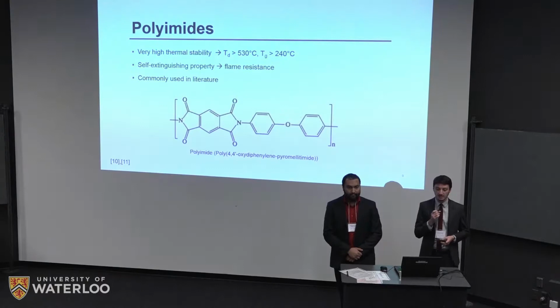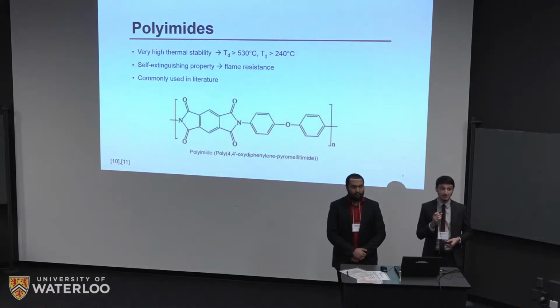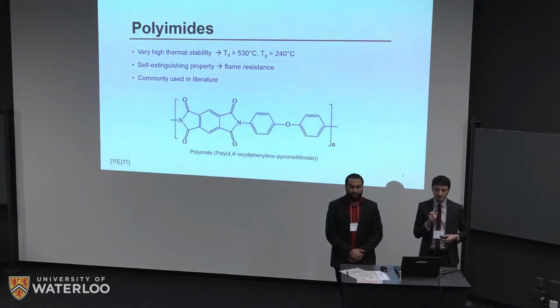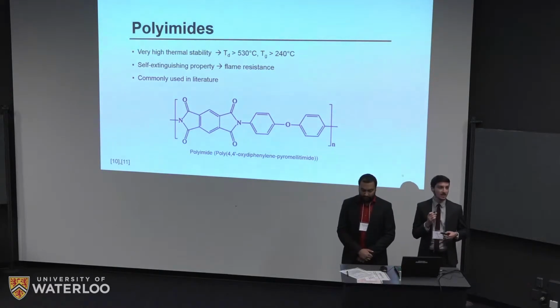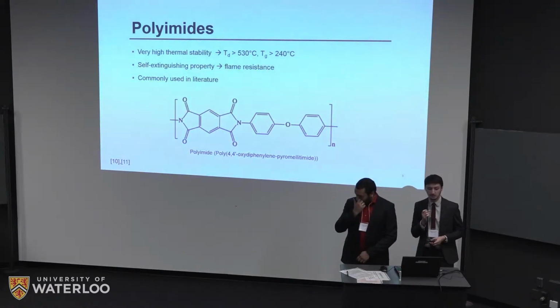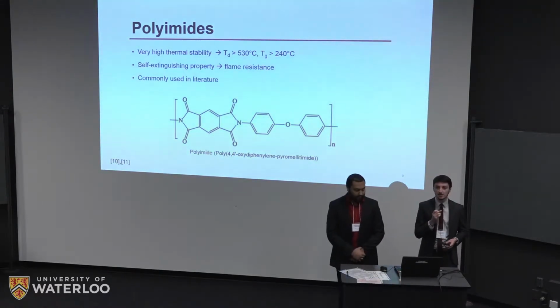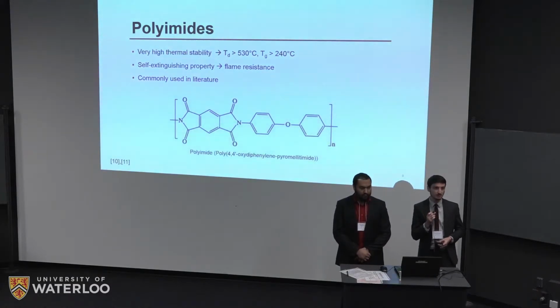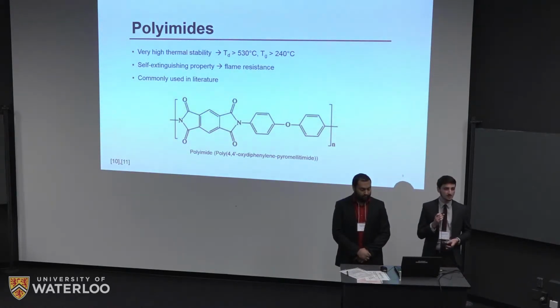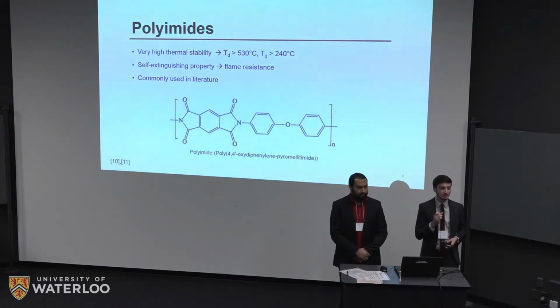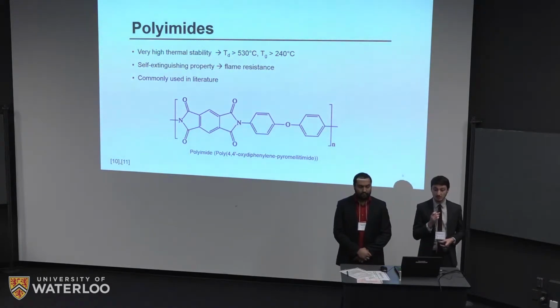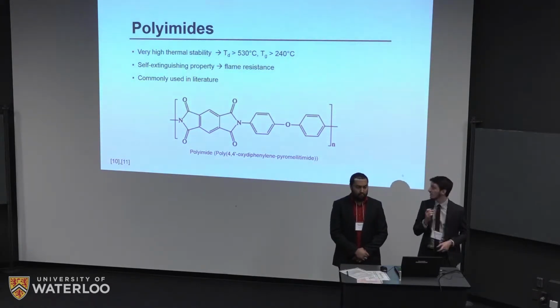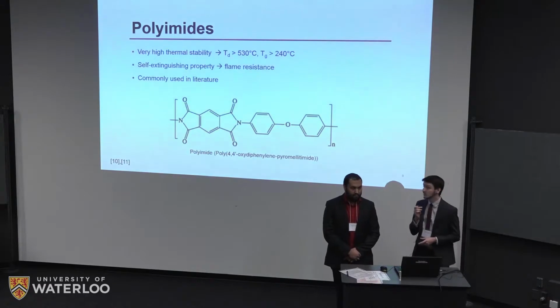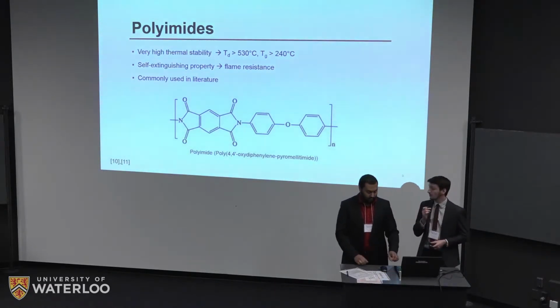So the reason we chose polyimide as our base polymer is because it has a very high thermal stability. It has excellent thermal degradation temperature and glass transition temperature for a polymer material. It also has the unique property of being able to self-extinguish by releasing compounds that prevent flames from propagating on the surface. This is commonly used a lot in research and in the industry for heat-resistant applications that require polymeric materials. As you can see here, this is the structure of the polyimide we are using for our project.